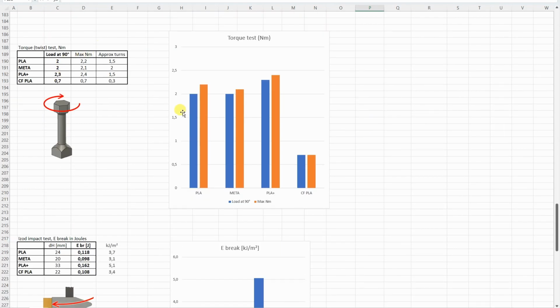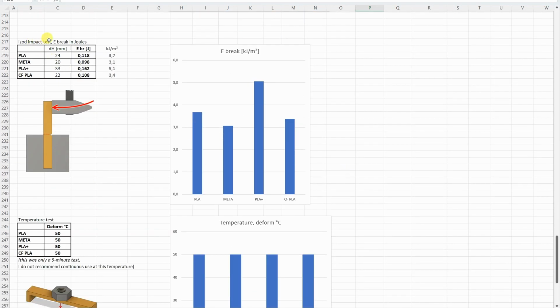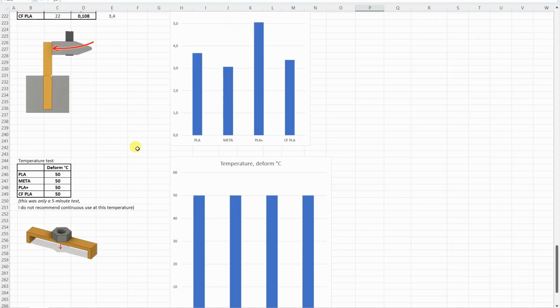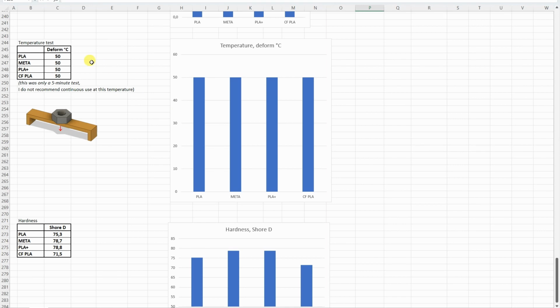The torque or twist test, again, these three filaments are very similar. Maybe the PLA plus was a little bit stronger. And thanks to that very weak layer adhesion, the carbon fiber PLA was very weak in this test too. The Izod impact test, here I measured the breaking energy, and interestingly, the PLA plus was the best, and then the other filaments were very similar. The temperature tests basically don't affect PLA too much, so they deform at approximately 50 degrees Celsius.